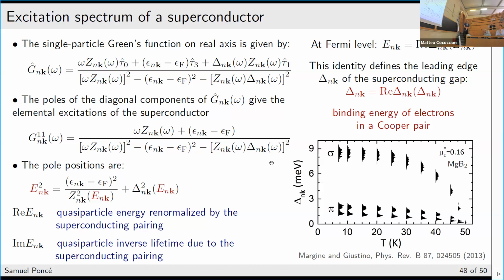Yeah, this is relatively common for this theory to overestimate. Now, how much it depends. I think what is nice is that this typically overestimates the Tc, while maybe the Allen-Heine one typically underestimates it, but it's not always the case. But then you can sort of sandwich where you are.